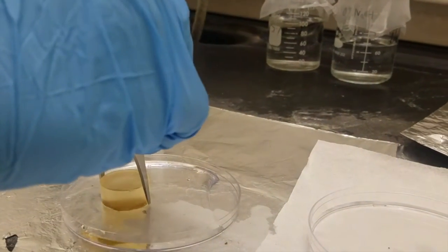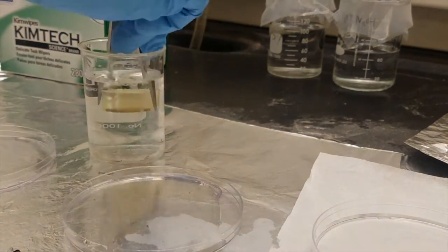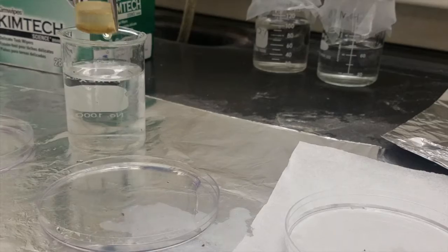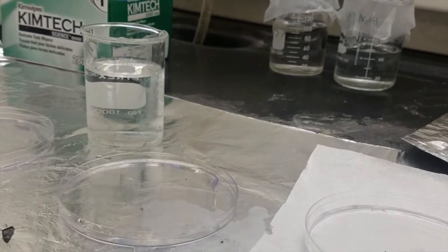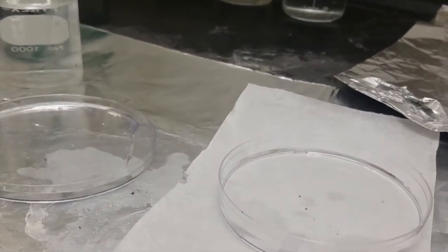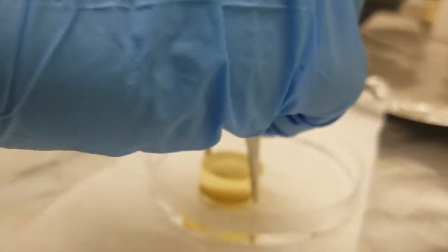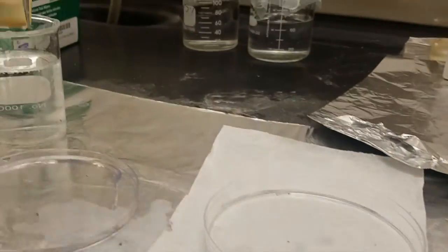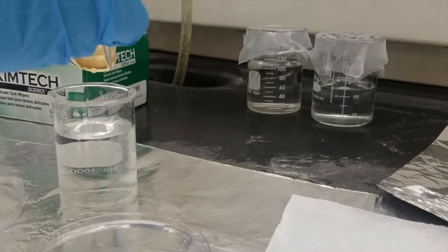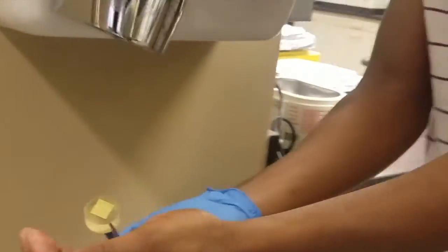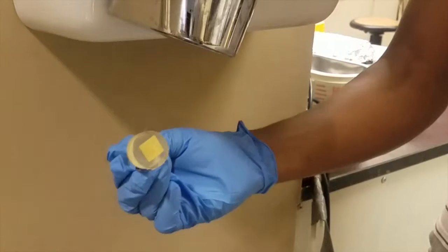The first etchant allows the grains to be visible. The second etchant will make the grains appear different colors under the microscope to distinguish them better. Between the etches, rinse the sample in distilled water. Do not over-etch the samples or images under the microscope will not be ideal. Once the samples are etched, they can be taken to the confocal microscope for imaging.